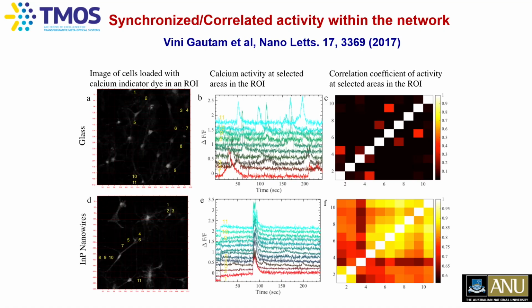And again, when you grow these neurons on glass substrates, there's a change in fluorescence as a function of time. You can see these neurons are randomly firing, and you see very little correlation coefficient here. Whereas the neurons grown on these indium phosphide nanowires are all firing at the same time. You see excellent correlation, indicating there is some sort of synchronized and correlated activity taking place. When Vinnie presented this work at a neuroscience conference in Melbourne, neuroscientists were quite excited about this. They started asking her what neurons she was growing. She said she's growing mice neurons.